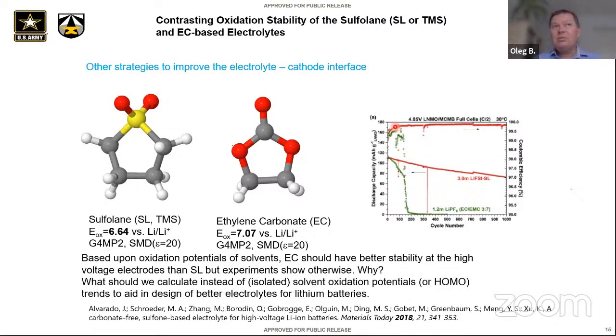Can we even get some trends? I mean, we can maybe calculate the oxidation potential of sulfolane versus EC and say that EC has a better stability by itself. So would it correlate? And the same with HOMO-LUMO. HOMO-wise, EC would have a higher stability, but does it correlate with the actual performance in batteries? Maybe in some cases it does, but in the case of graphite with lithium nickel manganese oxide spinel, which is a high voltage system, what we see is the opposite correlation.